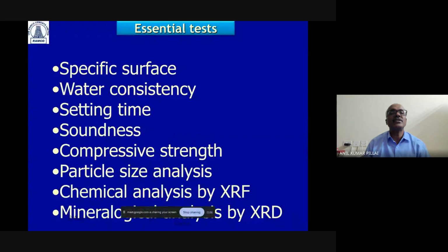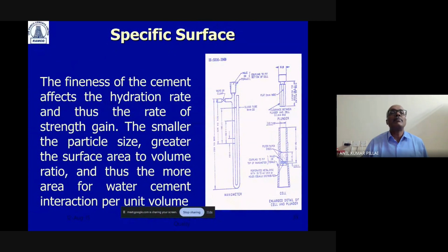So these are some of the essential tests that can be done on cement: specific surface, which we call the fineness, the consistency, the setting time, the soundness, the compressive strength, and the particle size analysis, which is not mentioned in BIS, but we do it on a regular basis because based on the particle size analysis of cement, you can control the quality of cement to a greater extent, and you can monitor it. And this particle size analysis and the chemical analysis by XRF and XRD are not in the purview of BIS itself. They are not saying it. But if we adopt these three methods of testing cement, we are able to look at the way cement can be customized. Because customization of cement is only possible if you have a detailed analysis and study of cement itself. So there, particle size analysis and chemical analysis by XRF and XRD play a vital role.